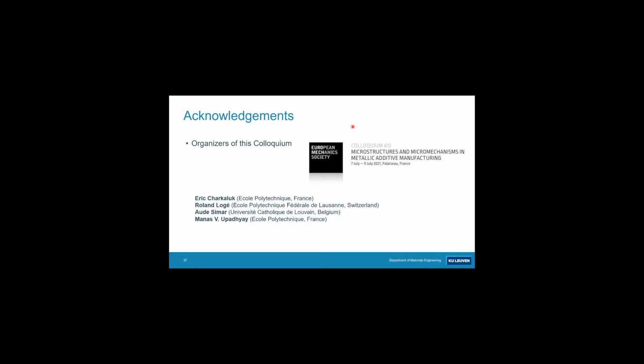So it would be very interesting to collaborate with people who, for example, in a synchrotron, could in situ visualize what is happening in these melt pools. And I had some presentation yesterday that we're able to do that. Yes. Collaboration is needed here. Yeah, indeed. Yeah, we've seen in zirconium containing aluminium alloys that we use for inclusions and for grain refiner that indeed it changes the interaction with the laser, and the processing conditions are different actually. So I think I see the same for aluminium.